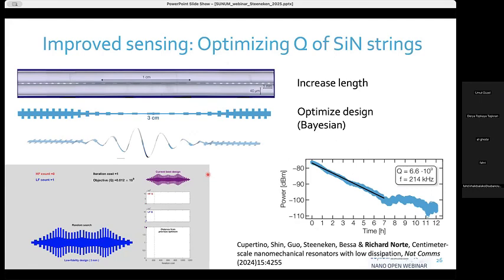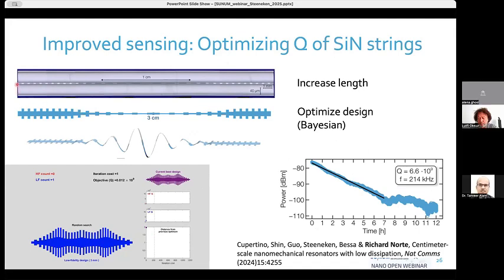Besides 2D materials, we are also trying to work with these string resonators, which are made out of silicon nitride. And I just want to show you one slide because I think it's quite a nice result. This is with my colleague Richard Norte. And here the goal is to limit the damping as much as possible to make extremely sensitive sensors. So it's a slightly different topic. But what we did is we created these silicon nitride resonators. So these are strings which are 3 centimeters long.